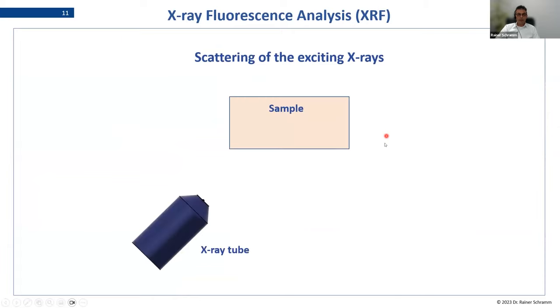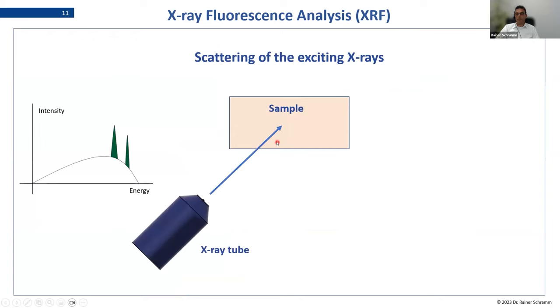So there would be another possibility to do an empirical matrix correction. This is if you want to use the scattering of your exciting X-rays. So let us assume we have our sample, and the sample is irradiated by our X-ray tube. The X-ray tube is issuing a spectrum more or less like this. So we have our continuous Bremsstrahlung, and we have our characteristic lines from the anode material of the tube.